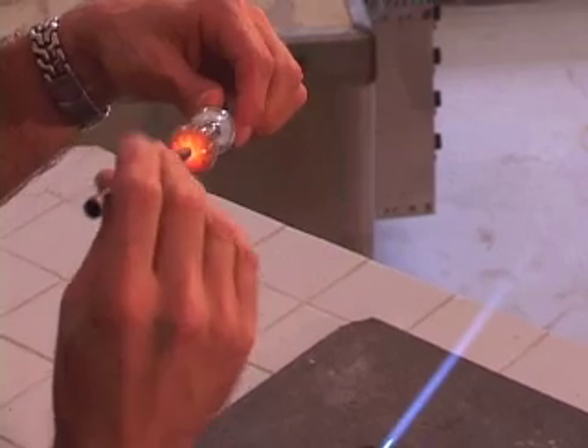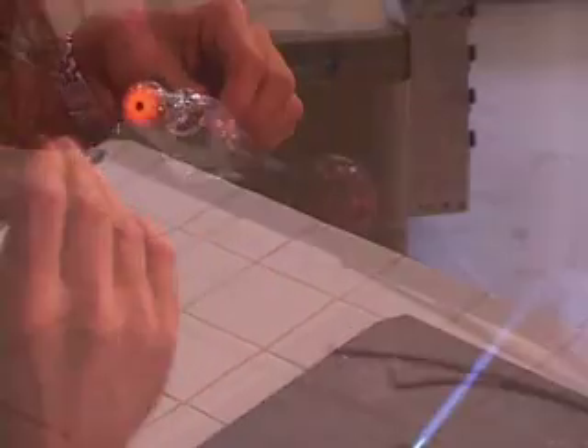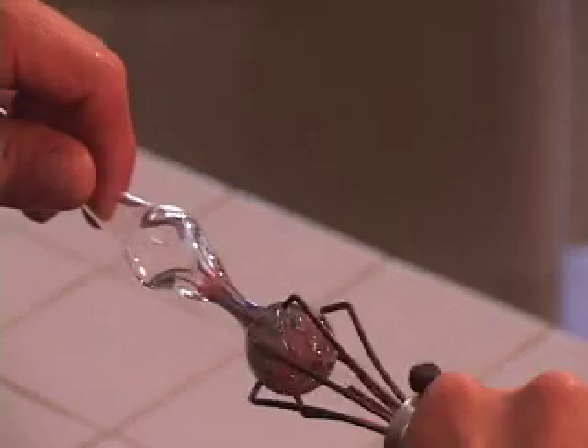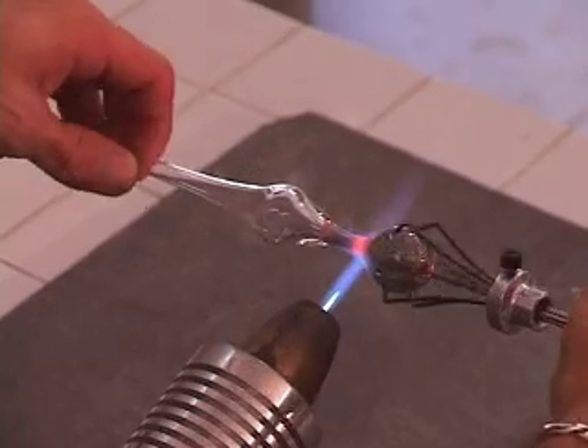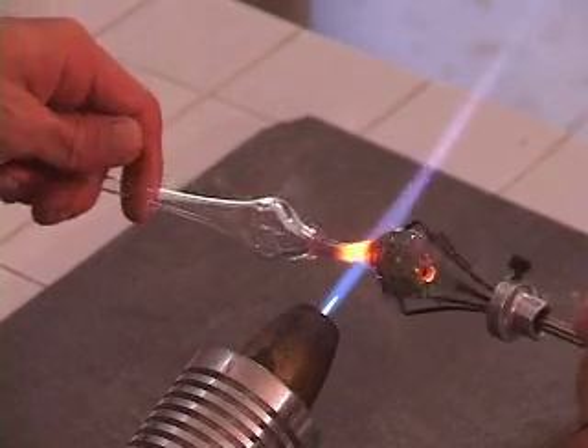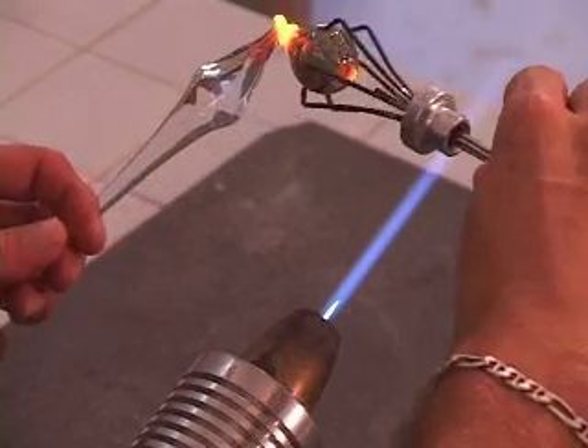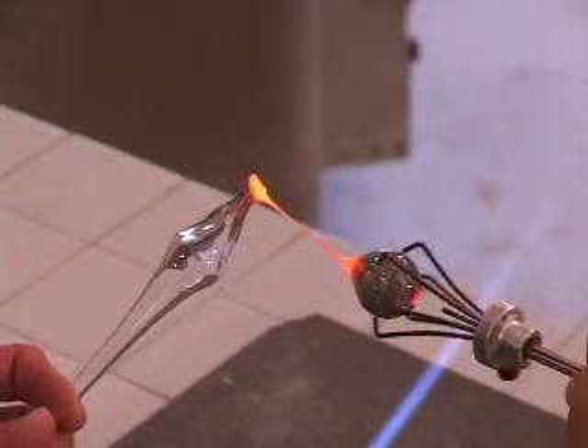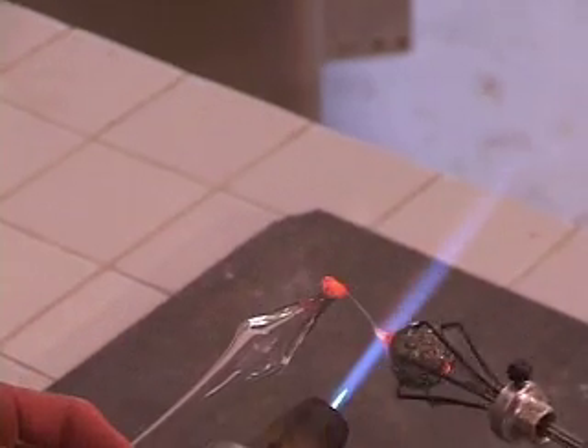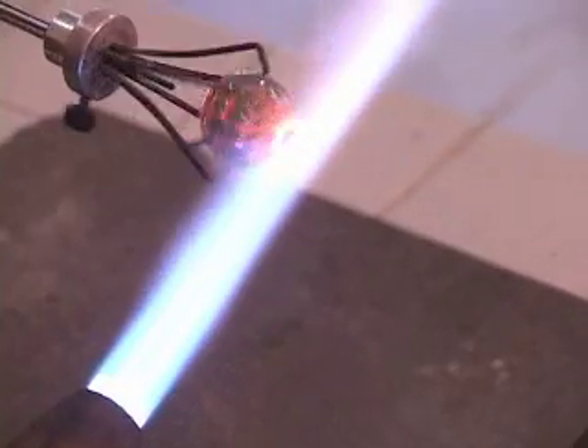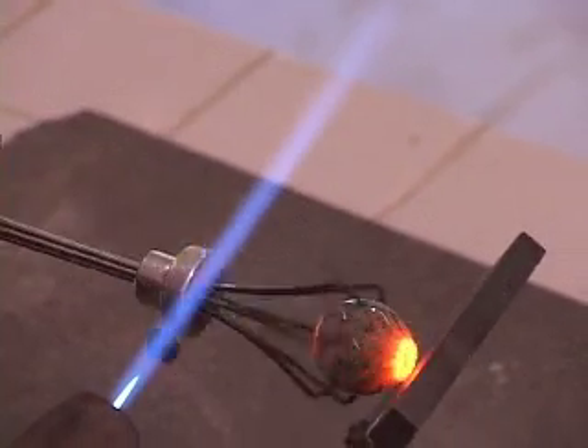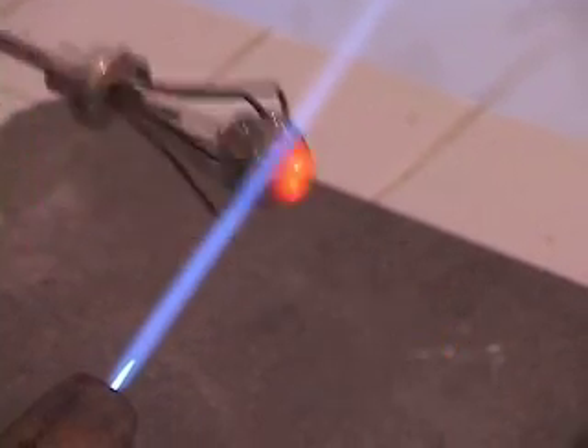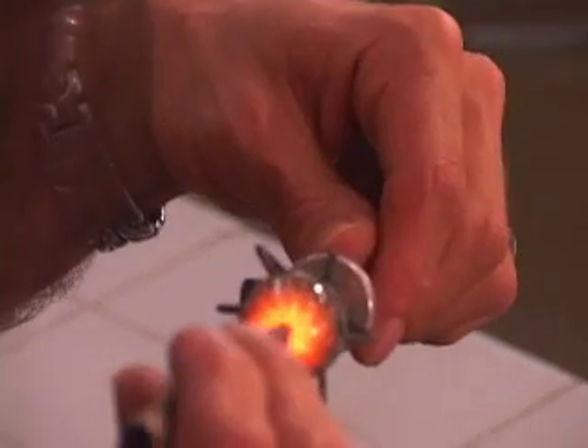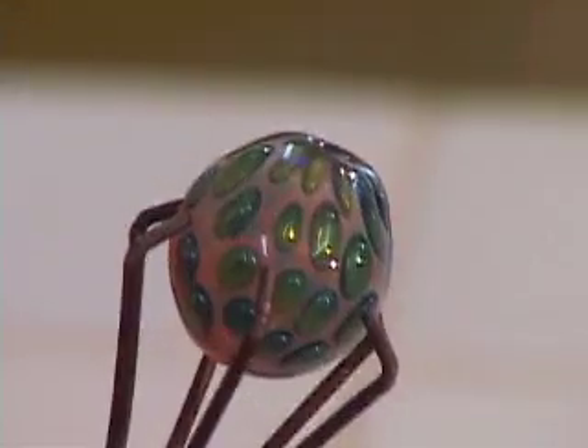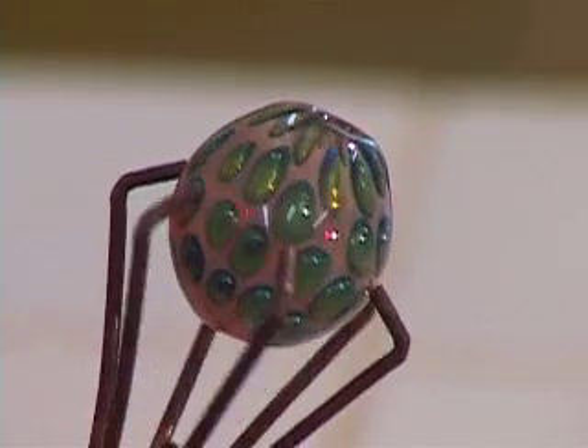With a pointed piece of carbon rod, define the shape of the hole. Using a claw grabber, grab your bead securely. Stretch off excess glass and open the other side of your bead. Heat and marver to shape the second hole. Take your finished bead and place it in the kiln at 1050 degrees.